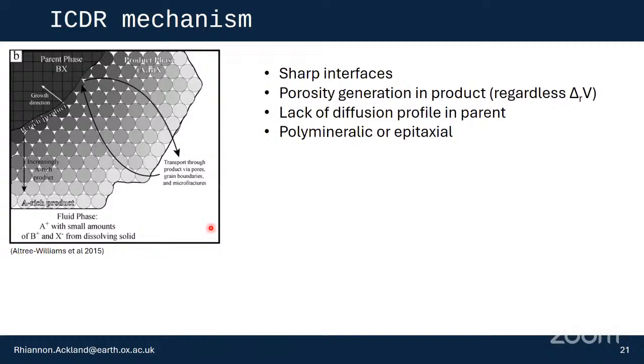So, a little bit about the mechanism that we think these rims are grown by. Rather than a simple diffusive system where cations are diffusing from the olivine through the OPX to the quartz interface to cause crystallization of orthopyroxene, we actually consider that an interface-coupled dissolution-reprecipitation mechanism is occurring.